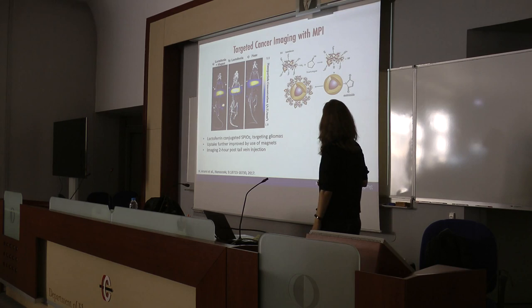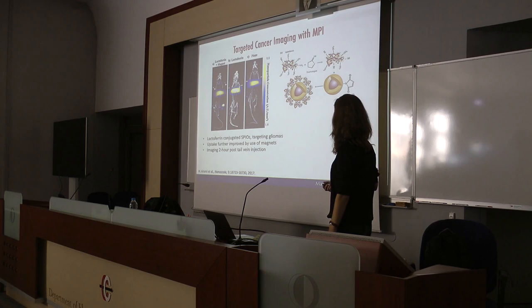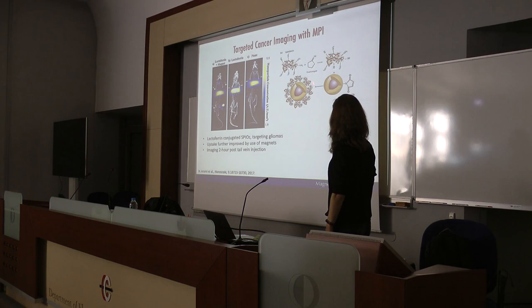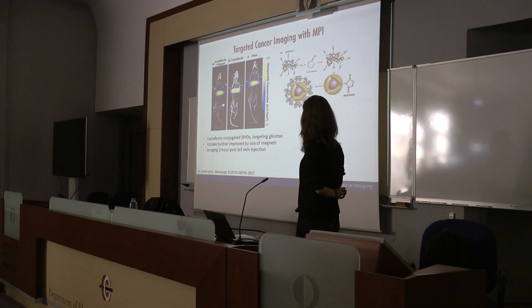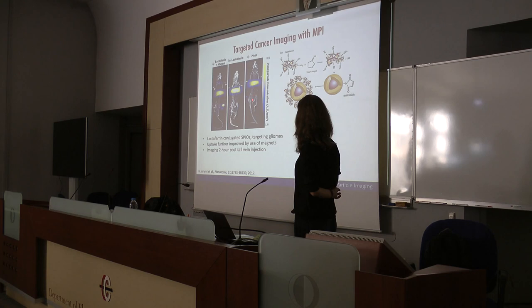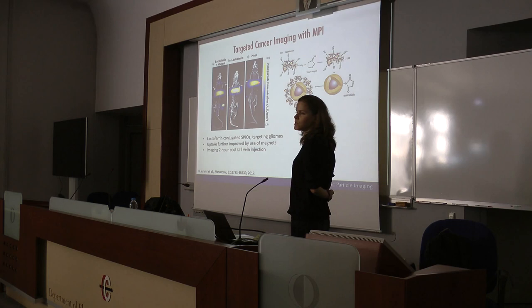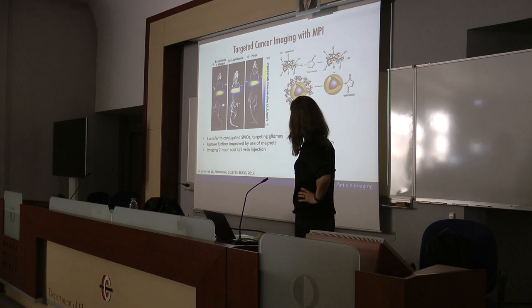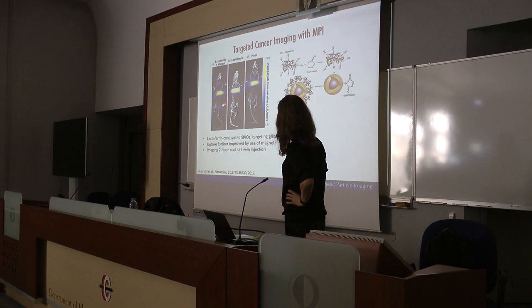There have also been studies on targeted cancer imaging with MPI. The surface of nanoparticles can be coated with chemicals that target tumors — in this case, lactoferrin was coated on the nanoparticles to target brain tumors (glioma). In the control study with normal SPIOs, only the liver lights up. With lactoferrin-conjugated SPIOs, more signal appears in the tumor region. Additionally, a magnet placed behind the tumor region further increases the uptake of iron oxide at the cancer location.